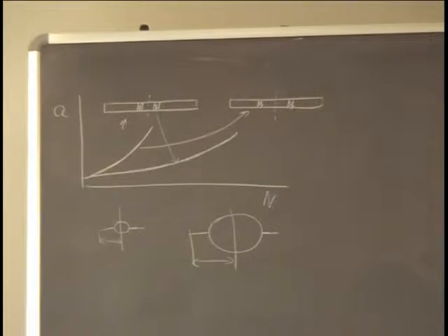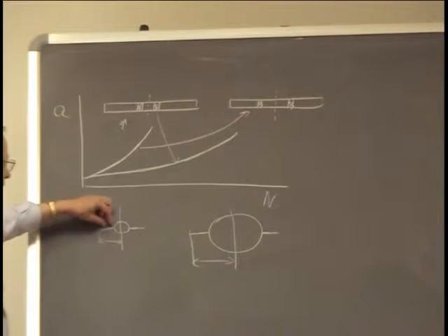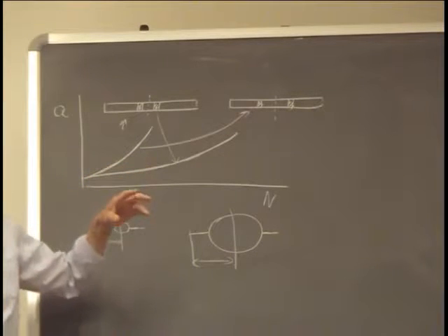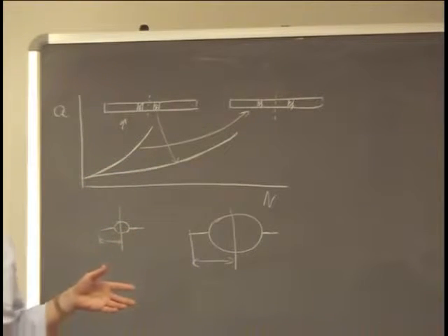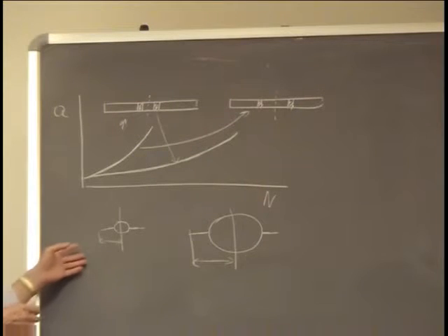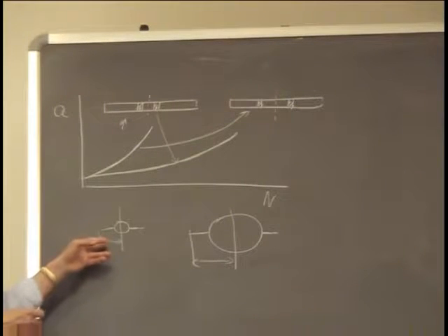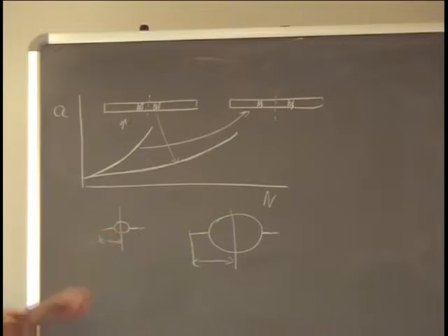In the beginning, it behaves really like a small crack here, a short crack, suffering, so to speak, from the stress field of the notch, in this case of the circular hole, and then gradually the effect of the hole diameter takes over, and this, I can tell you, is frequently being ignored. And as far as I know, this was the cause of the Alexander Kielland failure.